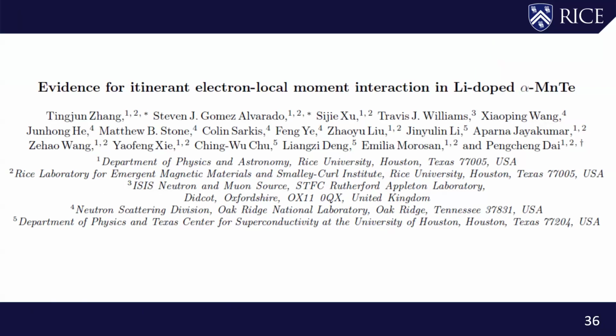So now let me move on to talk about the second part of the work that we were discussing. This is basically done by Pengcheng Dai and Stephen Gomez Alvarado. So this particular experiment is to try again to answer this very simple question. As I said earlier, altermagnetism basically requires the local environment to be different between the nearest neighbor manganese ions, and it should in principle be completely independent of the direction of the moment, right? As I mentioned earlier, the chromium antimony would have a moment along the c-axis, which is an altermagnet, and then the manganese tellurium, which has a moment in the plane, is also an altermagnet. But in the case of chromium antimony, there's no anomalous Hall, at least not in bulk, whereas in manganese tellurium there is. So one immediate experiment we wanted to do is to ask what actually happens if you dope lithium onto the manganese tellurium.